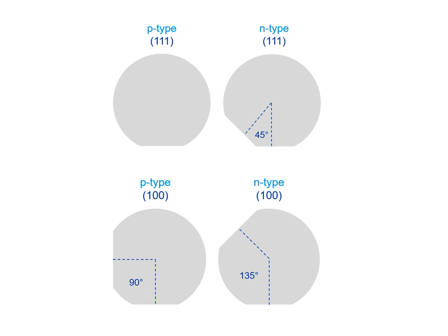But if we consider the P100, there is a primary and a secondary cut. One cut is less than the other one, so the lesser one is the secondary cut, and the angle between primary and secondary is 90 degrees in case of P100. But when the angle in between is 45 degrees, it becomes an N111 wafer. And similarly, when it becomes 135 degrees, it will be N100.